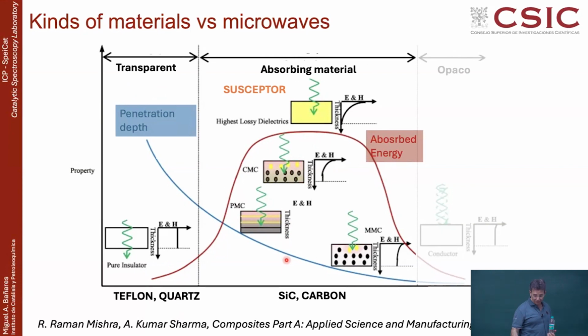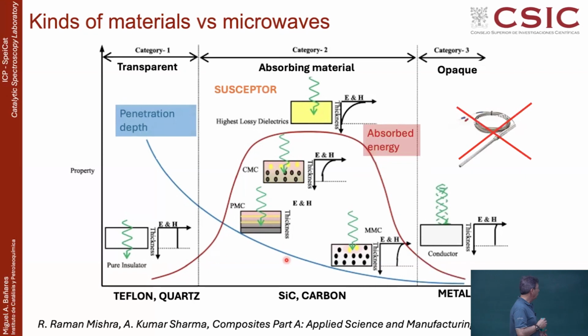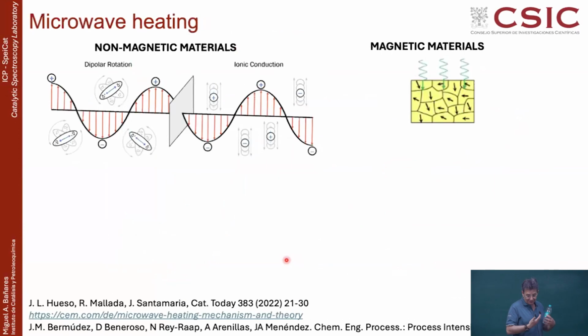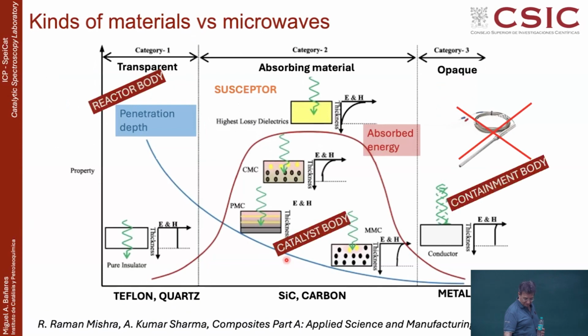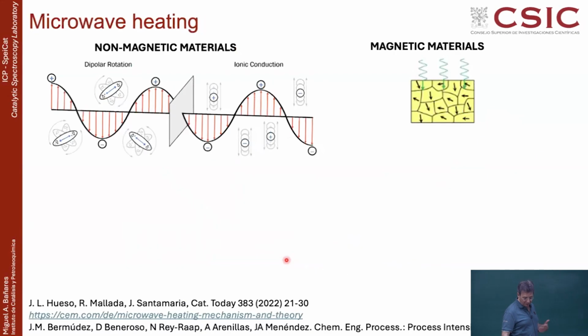And then you have another kind of material, which is the opaque one. The opaque one is a material that does not allow the microwave to go through, and that doesn't get heated by the microwave. So it's good for nothing? No, that's the containment. All the microwaves are metallic shielded because the metal doesn't heat and doesn't allow the microwave to propagate. So that is very interesting. For that reason, we are using this transparent material as the reactor body, this absorbing material as the catalyst body, and the opaque part basically as the containment. Okay. So this is kind of the design that you will see on these materials.